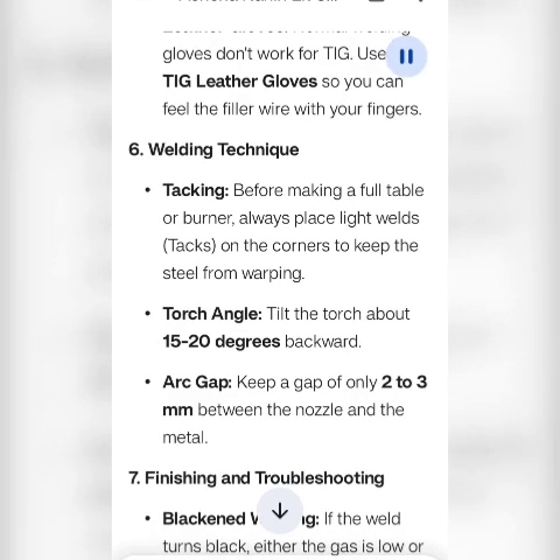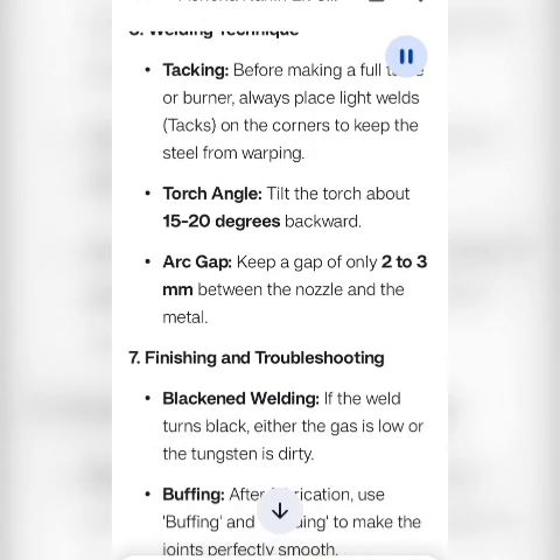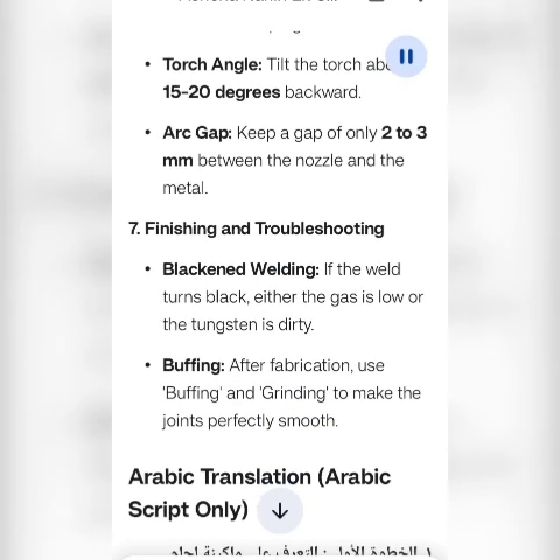7. Finishing and troubleshooting. Blackened welding. If the weld turns black, either the gas is low or the tungsten is dirty. Buffing. After fabrication, use buffing and grinding to make the joints perfectly smooth.